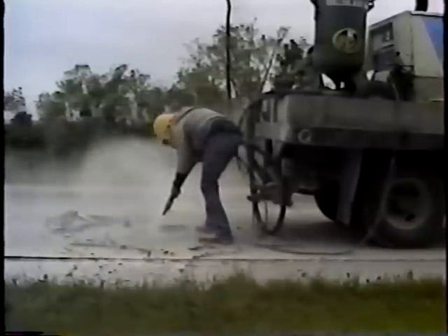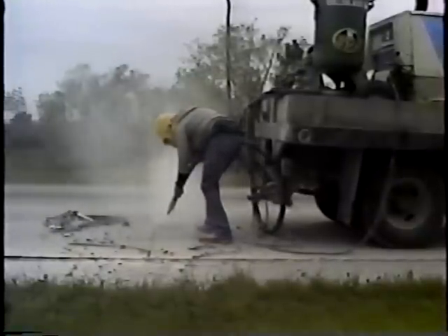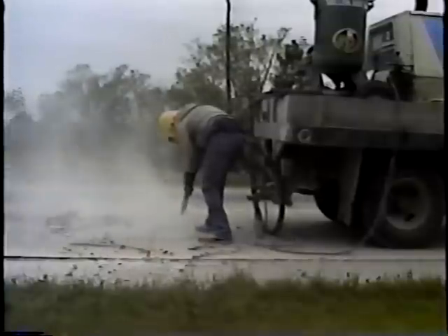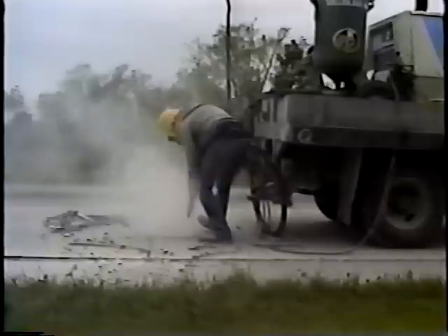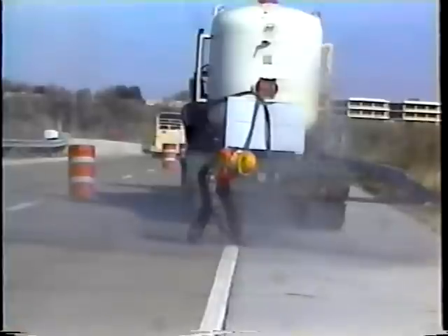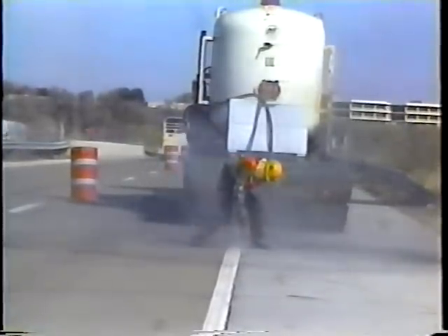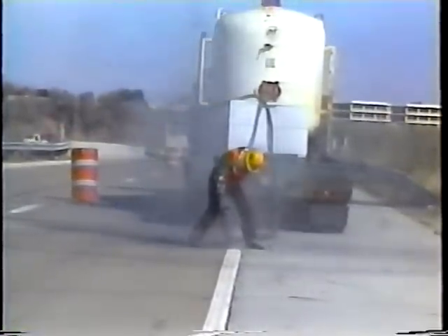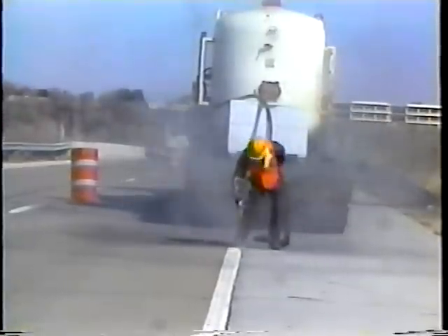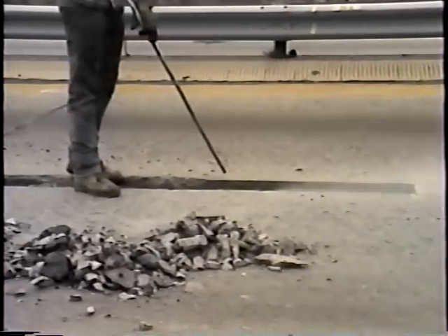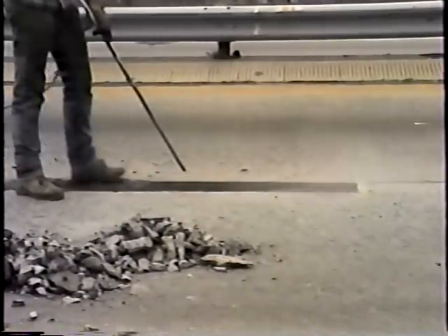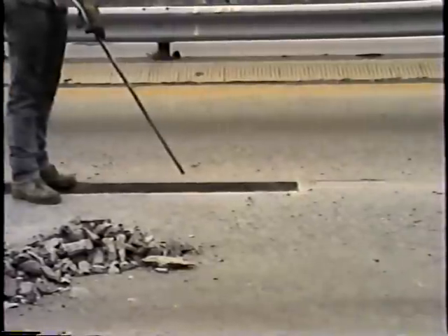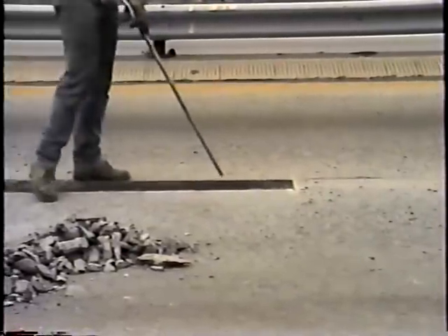But regardless of the method used to remove deteriorated concrete, the repair areas must then be thoroughly cleaned of all residue. This is best accomplished by sandblasting and air blasting. Sandblasting cleans the surface of dirt, oil, and other residue. It's also capable of removing the last particles of unsound concrete. Air blasting removes any remaining residue. It's important that the compressed air be free of oil, because oil sprayed onto the surface will hinder bonding. After cleaning, you should be able to rub the surface without picking up any dust or other contaminants.